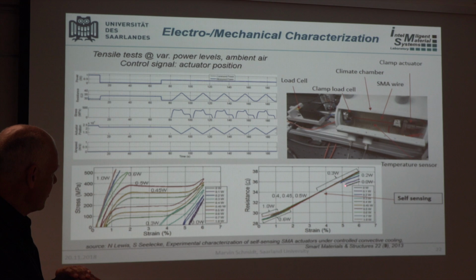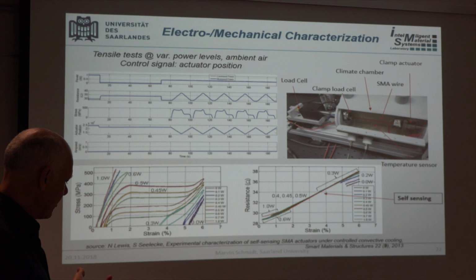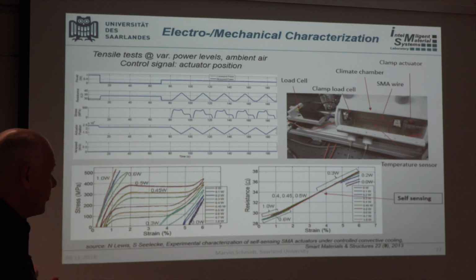So I now see the resistance has the 2 mechanisms of deformation dependence, changing L and A, and also the temperature. But even more, when I increase this to the level where it starts to transform into austenite, the phase transformation comes into play. And it's phase transformation because austenite and martensite have different resistivities. So you have phase transformation, you have temperature dependence, and you have deformation dependence.